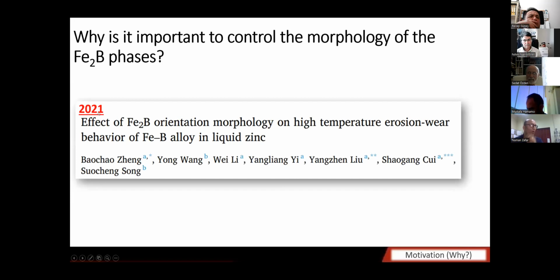In November 2021, this paper was published while I was trying to find a way to control the morphology and orientation of Fe2B phases. This study has reported the influence of the morphology of the Fe2B phases on the erosion wear behavior of, again, iron boride alloy.